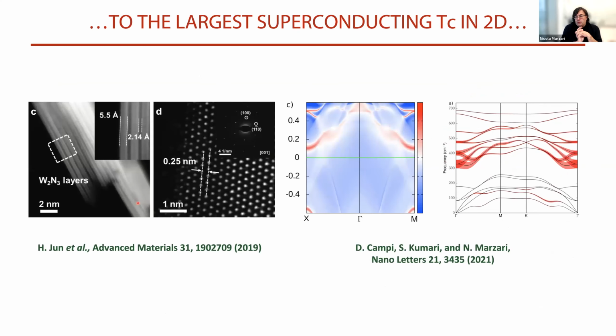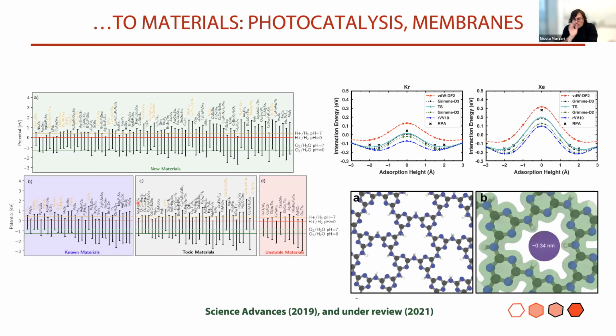Let me give you a few examples of work in progress that is starting to look interesting. We are looking for new superconductors, and this material that you see can be synthesized extremely well into layers. We have a prediction right now of a transition temperature of 22 Kelvin. That would be a world record for a 2D material, and in particular is higher than liquid hydrogen. And there are a number of groups that are trying not only to make this material, which requires very difficult high pressure synthesis, but also to exfoliate it. We are also looking at materials for photocatalysis or membranes for separation.